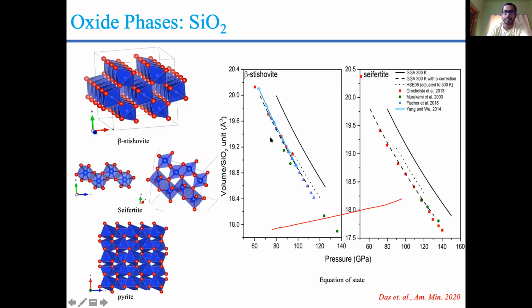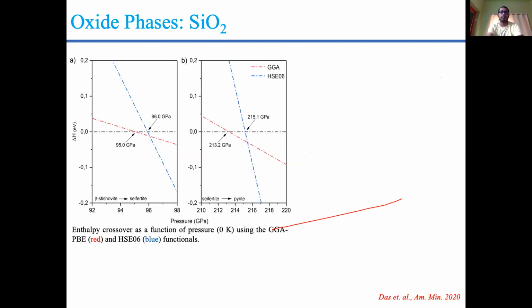So after this correction, we started our calculation with the transition pressure, because their transition pressure is well studied but not well verified. So here I used two types of functionals, GGA and hybrid, and found that hybrid always predicts a little bit higher volume, higher transition pressure than GGA. So this is at the static level.